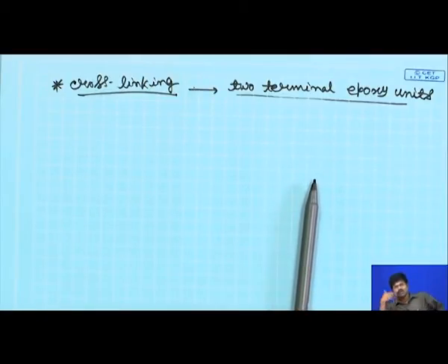That means, in order to get one equivalent of epoxy unit, you have to have more amount of the polymer. So, that means your epoxy proportion is lower. So, in that case your cross linking distance will be much higher. If you do not want to do that, then instead of using epoxy units as the cross linking points, you could use the secondary hydroxyl units that are present in the repeat unit of the molecule to also cross link.